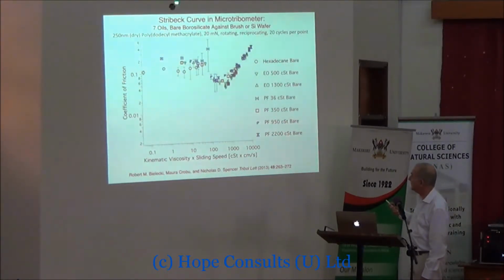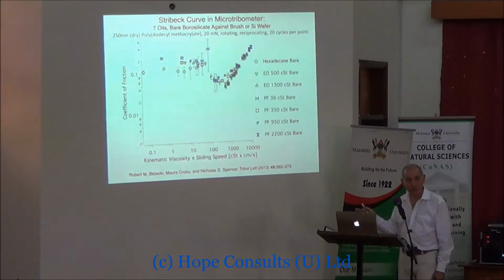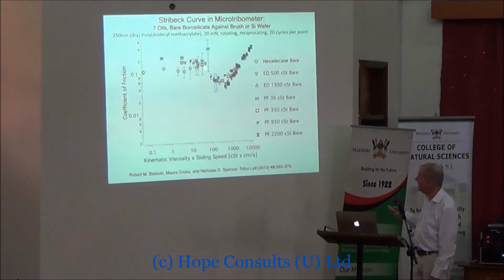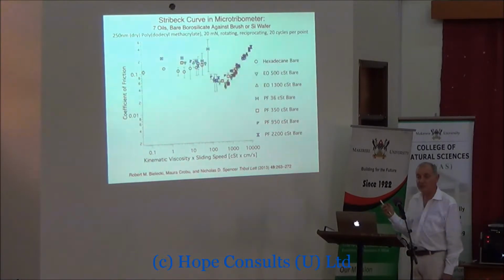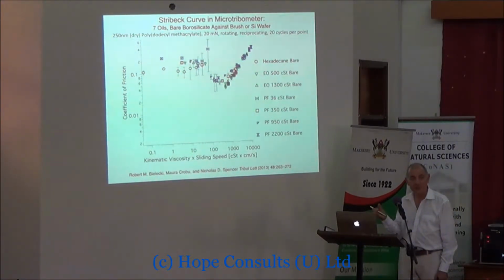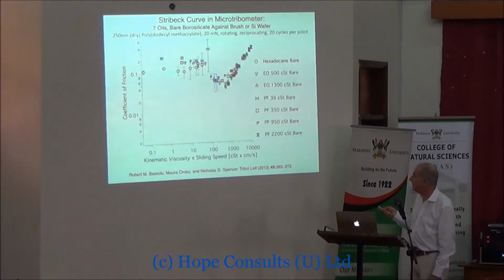Now, if we look at a number of different oils and their performance, here we have an example of a borosilicate bead sliding against a silicon wafer with no brush. There's no polymer in this top data I'm showing you here. And we see the Stribeck curve behavior again. Out here we have the boundary regime where we have the hard borosilicate bead just sliding against the silicon wafer with no hydrodynamic lift, so it's quite high friction and quite noisy.